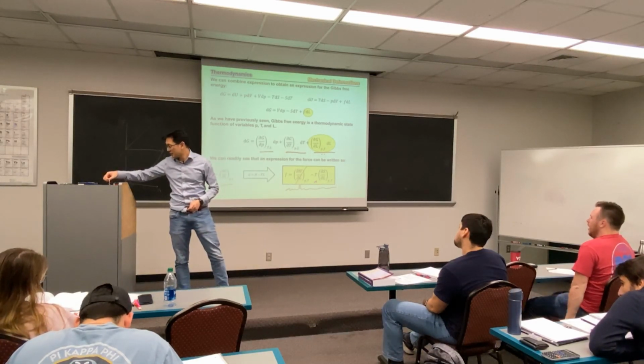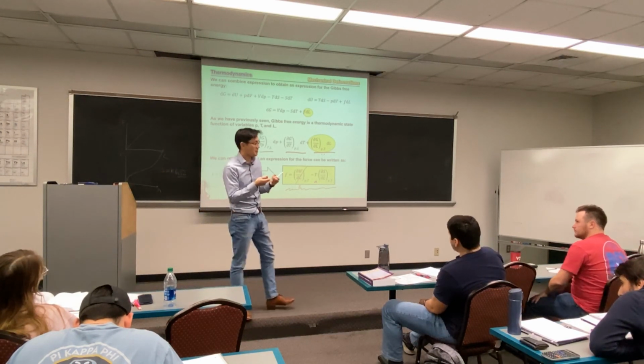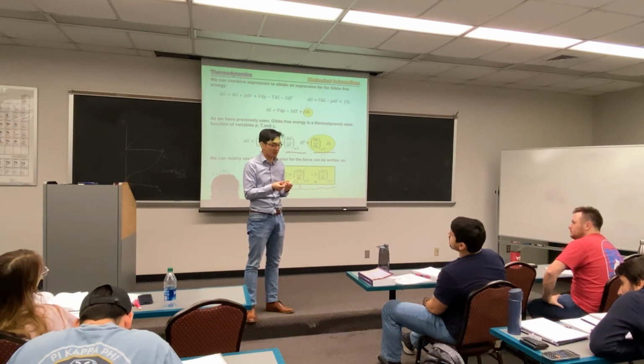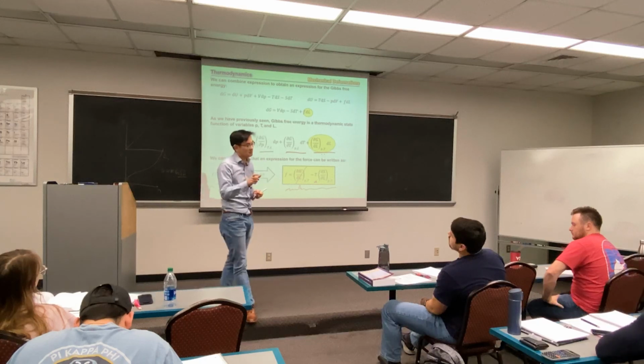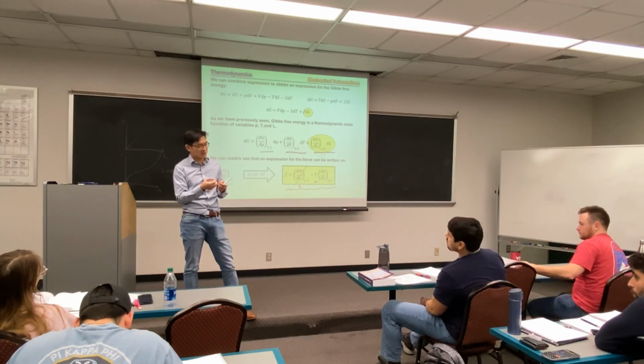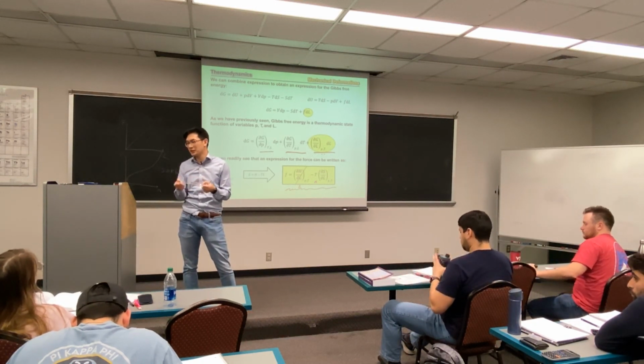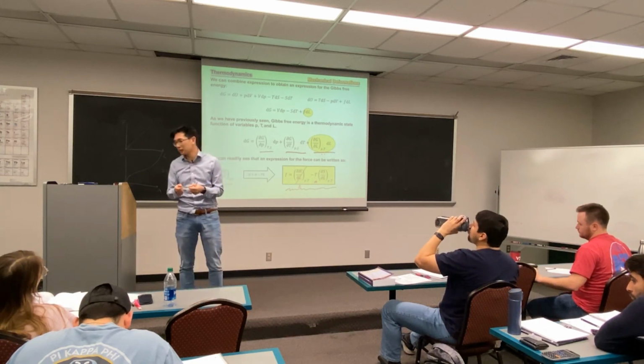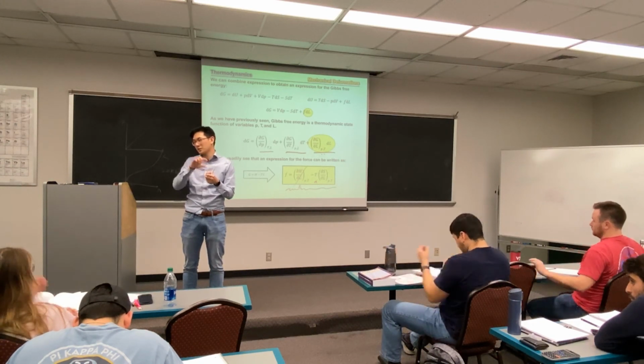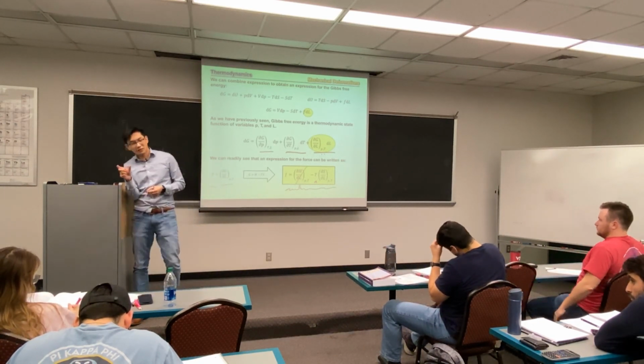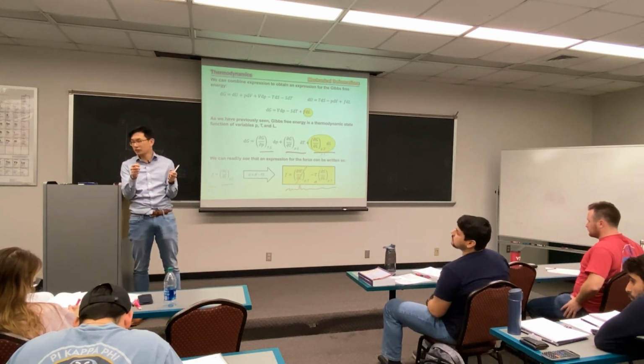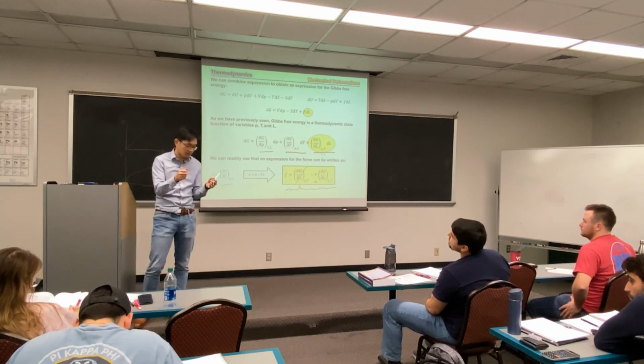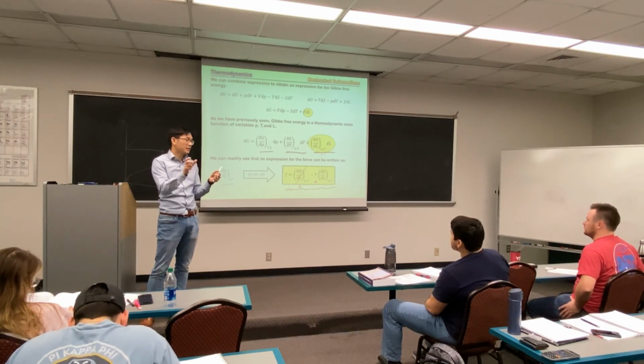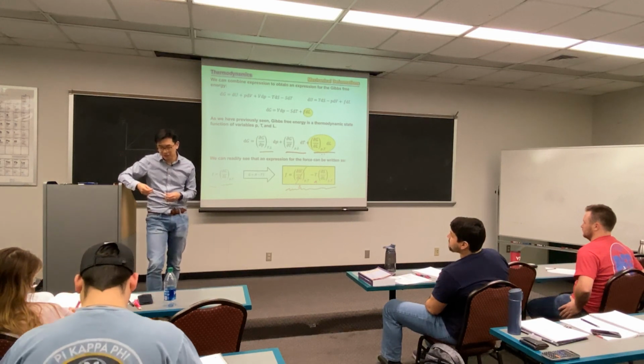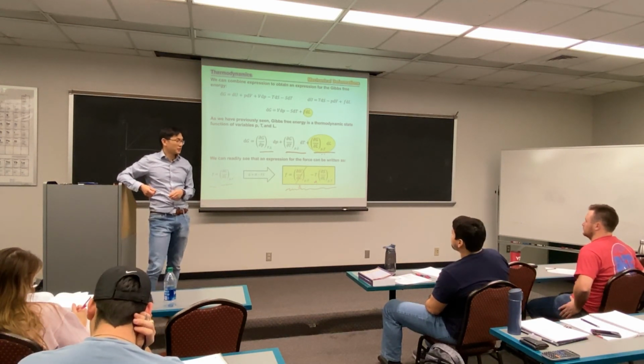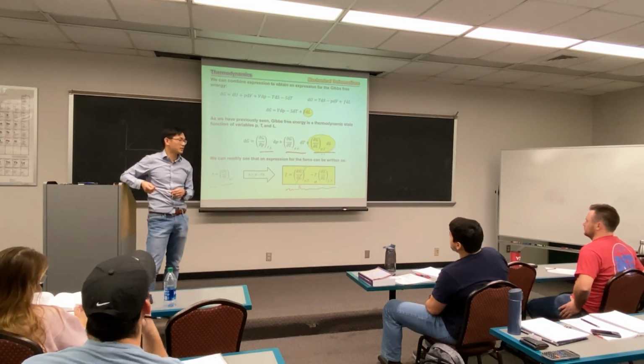As I mentioned to you guys a couple times, the modulus for the rubber band is on the megapascal level. And typical cross-link density in a polymer, or maybe it's easier for you guys to understand, a typical rubber material has long polymer chains. The molecular weight is typically on the order of hundreds of kilodaltons, very high molecular weight. There are multiple cross-link points along this single chain. And for each two cross-link points, if you measure the molecular weight between them, we call that the molecular weight of the cross-linked segments. They're typically on the order of a couple thousand daltons. So for a long chain, you have tens to hundreds of cross-link points along it.